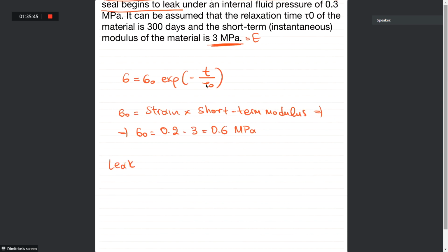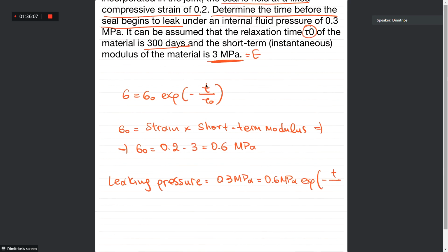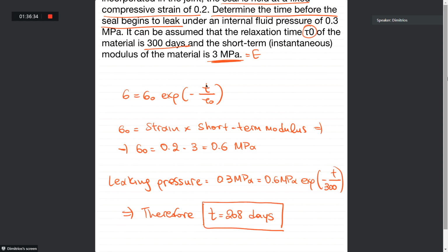So the leaking pressure equals 0.3 megapascals equals 0.6 megapascals times exponent of minus t over tau 0, and we know that tau 0 is 300 days, okay? So if you solve for that, therefore t equals 208 days, okay? So the seal will begin leaking at 208 days. It's very simple. It's just a substitution of the correct values into the Maxwell model for stress relaxation.